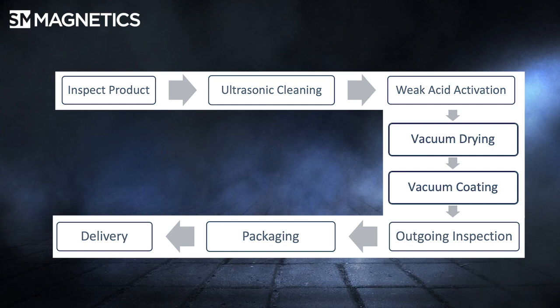Then we'll start the parylene coating process, done under vacuum as well, because we don't want any oxygen underneath the parylene material. It needs to go on as a thin film with no contaminants — we're not going to backfill with argon or anything else; we keep this all under vacuum. The parylene comes in as a powder — it's a powder dimer process — and we vaporize it. In the vacuum system it gets heated to around 150°C and starts to turn into a gas. We keep heating it up to about 700°C and it becomes a gaseous monomer, flowing through the vacuum chamber and coating everything inside. We hang the magnets or suspend them so the polymer can get all the way around them on all sides.